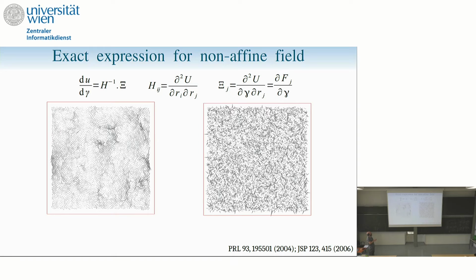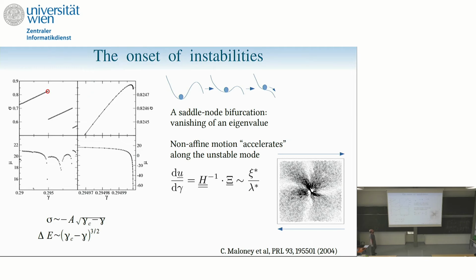And it's much more soft because essentially when you invert the Hessian, you pick up the lower frequency, you have a dominant contribution of lower frequency modes. And this is why you have something that looks very smooth, and this is your non-affine field. So I think the two key statements are first that non-affinity is a property of the linear response. And the second key statement is that it softens the system and that it has a direct effect on elastic moduli. Maybe a third statement, that's more technical, is that we can calculate all of that, and it's of course very convenient in simulation. And so that's just to summarize what I was saying.